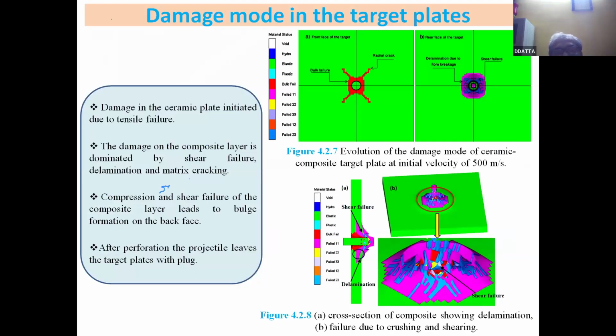These are some of the damage zones, damage modes in the target plates. This is the damage pattern for the ceramic part, front face of target. This is the bulk failure, and the most important evidence is the radial cracks. These radial cracks are typical for bulk failure of the ceramic. Whereas this is predominated by delamination due to fiber breakage and shear failure. And part of it is the plug formation, the shear plug that comes out from behind along with the projectile, if it perforates.